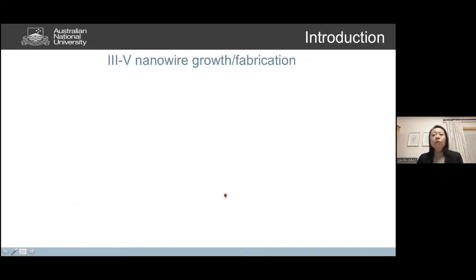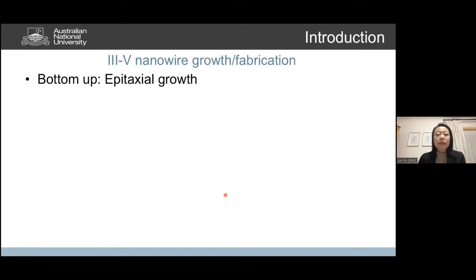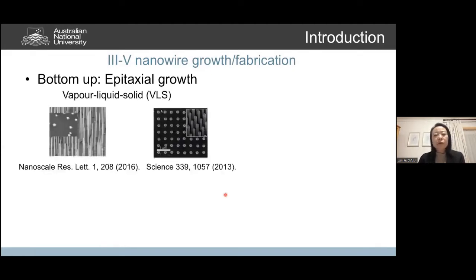So how do we grow nanowires, or how do we fabricate nanowires? Basically there are two approaches. One is the bottom-up approach using epitaxial growth. In this approach, a very common method people use is the so-called vapor-liquid-solid method, where we use metal nanoparticles such as gold as a catalyst seeding layer to promote nanowire growth. Of course, you can use colloidal metal nanoparticles and directly spray them onto the substrate, or you can use nanolithography techniques to create little gold nanodiscs to do position-controlled nanowire growth. But in this technique, you introduce a metal into your growth, which might sometimes create some challenges in device performance. And also the growth mechanism is based on this VLS technique.